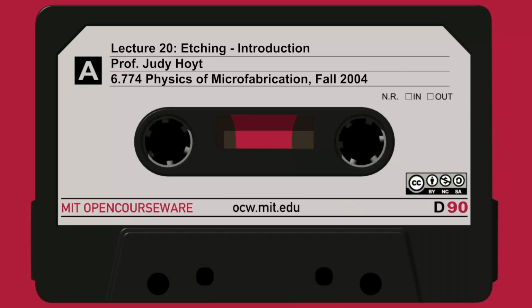Whereas on the right, I etched quite a bit because the etch rate of the silicon is much faster than it is in this case. Okay. Now I form again, in the next step, a little bit of inhibitor deposition on both the left and the right. Here the inhibitor dep rate is pretty fast, so I have a thick inhibitor. Now during the etch part, I etched just a little ways, whereas here, look, I etched a deep ways. And you continue on doing that, and you can see that in the left case, you're going to end up with a more sloped sidewall because the inhibitor is going down much faster than you are etching into the silicon.